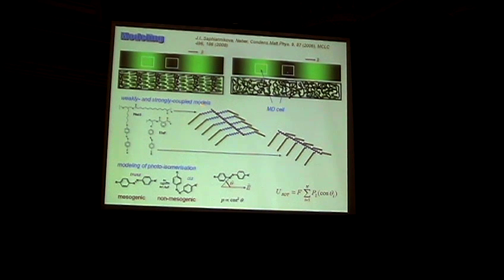To consider liquid crystalline and amorphous systems, we developed two semi-atomistic models. One is weakly coupled with long spacer, and the other one is strongly coupled with short spacer and with more rigid backbone.